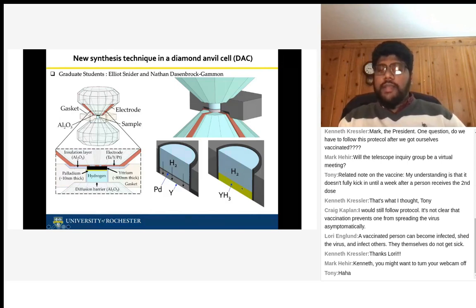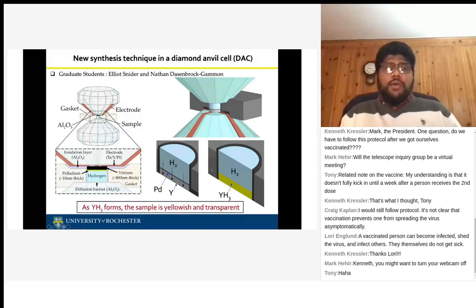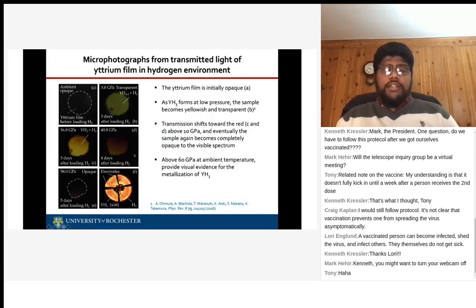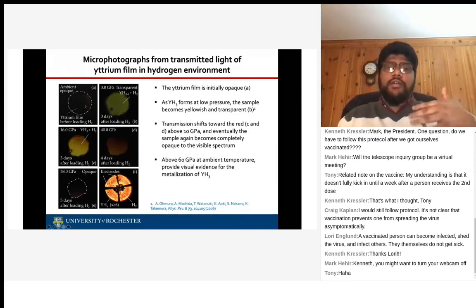So what really happened is, if you look at this zoom view of this image, you have yttrium, a tiny layer of palladium, and hydrogen. The hydrogen diffuses in and you make yttrium hydride, YH2 to start with. So pure metal is opaque, right? But as soon as you make YH2, when hydrogen goes into the yttrium, it is a transparent material. I'm going to show you this series of pictures to prove that. Here at ambient conditions, this is with transmitted light, so no light is coming through, maybe a tiny bit here, depending on the thickness of your film. And then as soon as hydrogen comes in, it reacts, you see this opaque area become a transparent yellowish color, which indicates that you're making yttrium hydride.